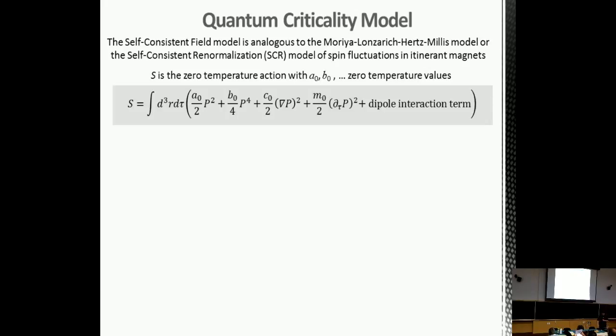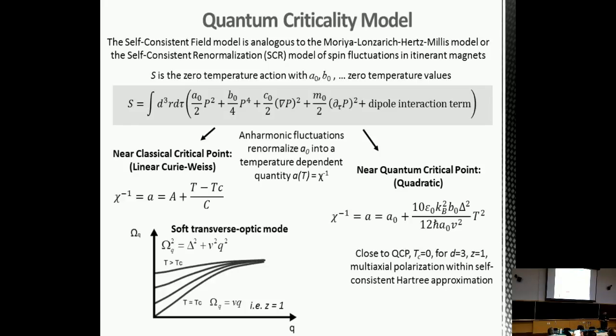And if we treat this using a self-consistent phonon model or self-consistent field model, which is analogous to the self-consistent renormalization model in itinerant electron systems, we can see that close to a classical phase transition, we recover the Curie-Weiss form, where the inverse electrical susceptibility varies linearly with temperature. But close to the quantum phase transition, the quantum critical point, the inverse dielectric susceptibility varies as T squared, quadratically.